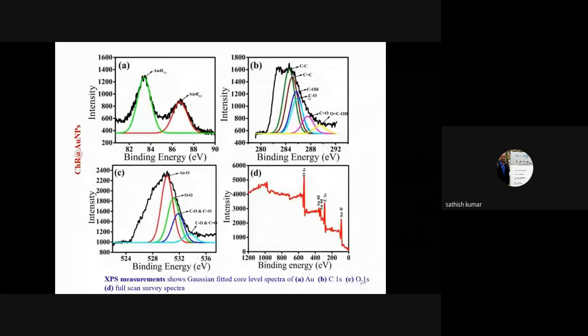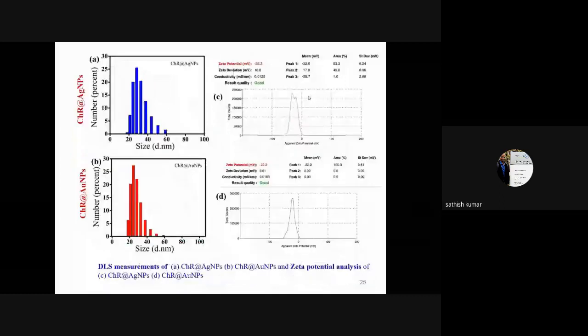This is a very important analysis. Size, we have studied the size, shape, and also the surface chemistry. Another important parameter is the stability. So whenever we develop a nanoparticle, it should be stable for a long period of time without any aggregation. So here the large negative zeta value clearly indicates that the particles are highly stable in aqueous medium.